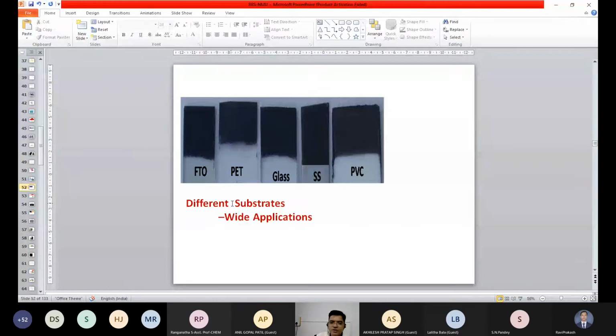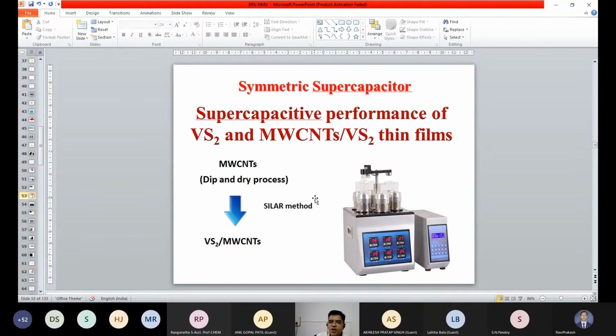So these are the different substrates that we have used for different applications, like FTO, fluorine doped tin oxide, PET, glass, stainless steel, PVC. So we have optimized this coating of the carbon nanotube depending upon what type of substrate we are choosing. And for the supercapacitor application, we are using stainless steel as a substrate, so that it is possible to have bending. So that is the first approach.